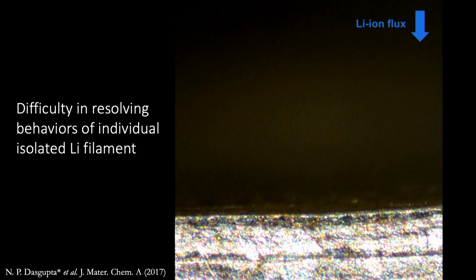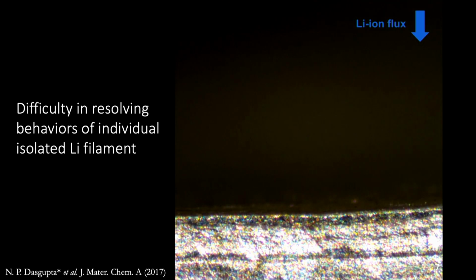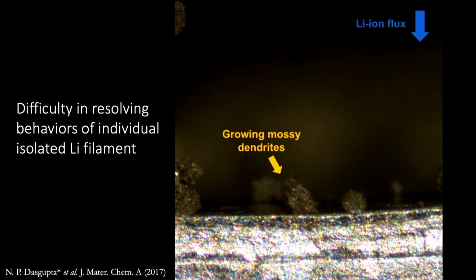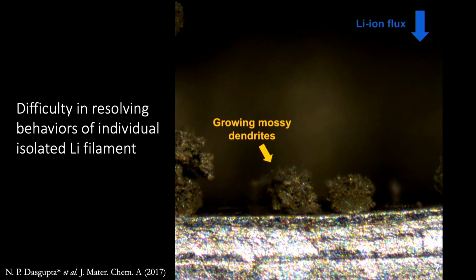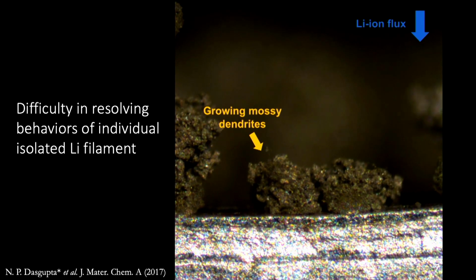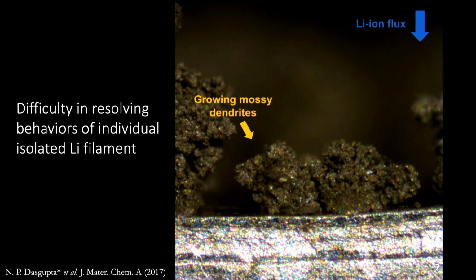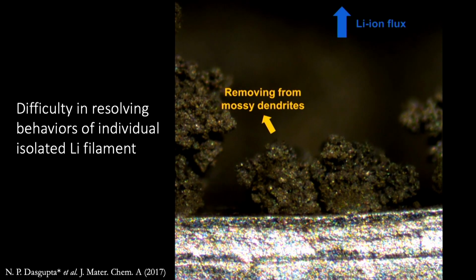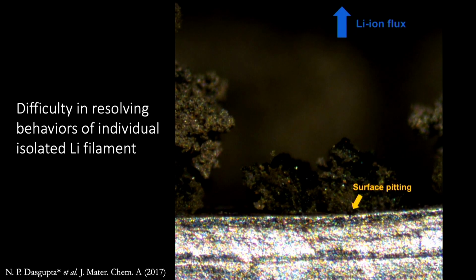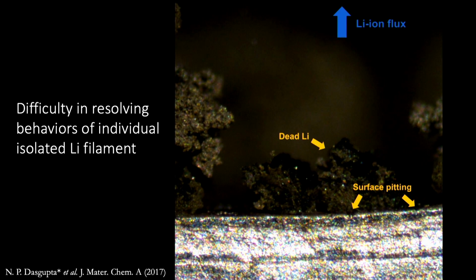How can we observe it? Before we designed our own setup, we looked at the literature to see what people have been observing for the last 20 or 30 years. This is work done at the University of Michigan. They're looking at the surface of lithium and the electrolyte during the lithium deposition process. You can see the formation of mossy lithium during the deposition process and also its dissolution process.